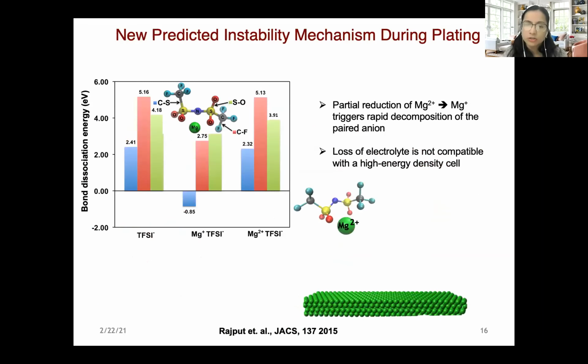So to test the stability of anion, we computed the bond dissociation energy of this TFSI anion, which is a measure of chemical stability of a molecule. And we tested the stability in 3 different media: the anion by itself, the case when an ion is paired with magnesium 2+, and the case when an ion is paired with this reduced transient magnesium 1+. And different bars here represent different bonds of this TFSI anion. And we observed the anion is pretty stable by itself. That's expected, right? And it's also stable when it's paired with magnesium 2+. But this carbon-sulfur bond becomes unstable when the anion is paired with this reduced transient magnesium 1+.